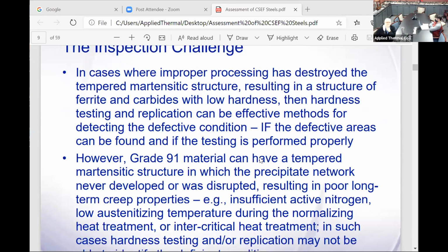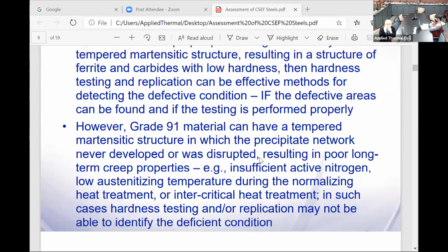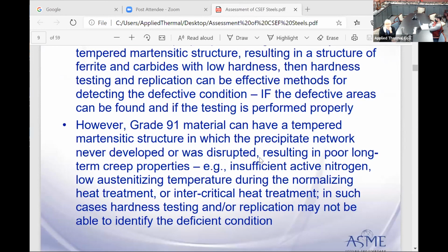So, in cases where improper processing has destroyed the tempered martensitic structure, resulting in a structure of ferrite and carbides with low hardness, then hardness testing and replication can be effective methods for detecting the defective condition, if the defective areas can be found and testing is performed properly. Grade 91 has the tempered martensite structure, and if that process was never developed or was disrupted, obviously you end up with poor long-term creep properties.